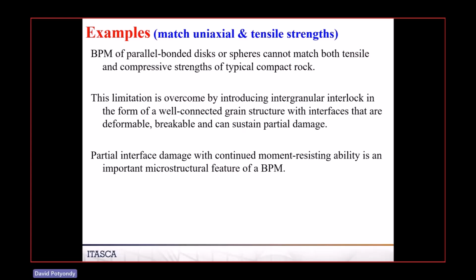So it turns out that if you just use parallel bonded material, discs and spheres, you're not able to match both tensile strength and compressive strength. You can match the tensile strength and then the compressive strength is too low. Now this is for a compact rock like granite. The compressive over tensile strength ratio of certain types of granite could be up to 30. The ratios that we get with parallel bonded discs or spheres are on the order of 5 or 6.